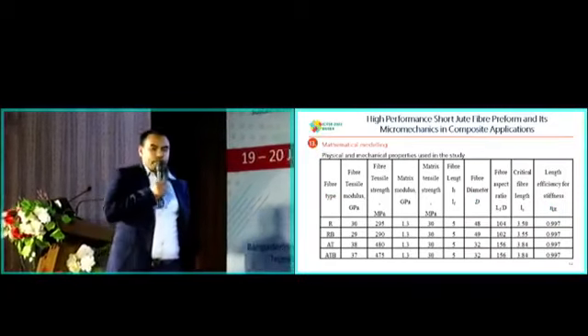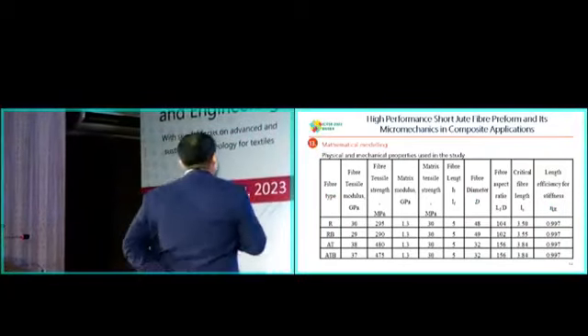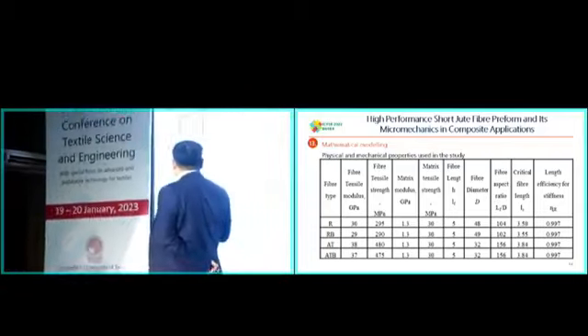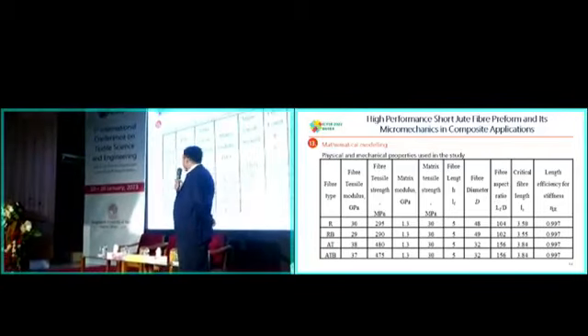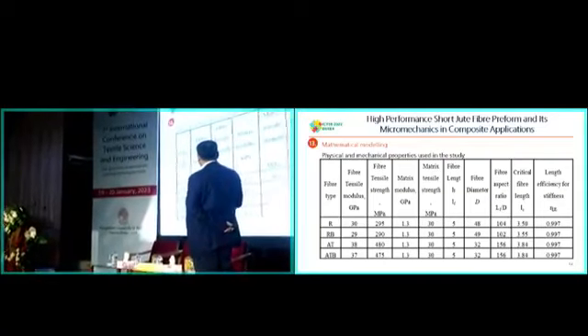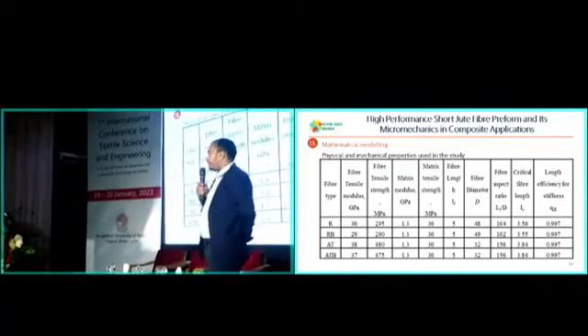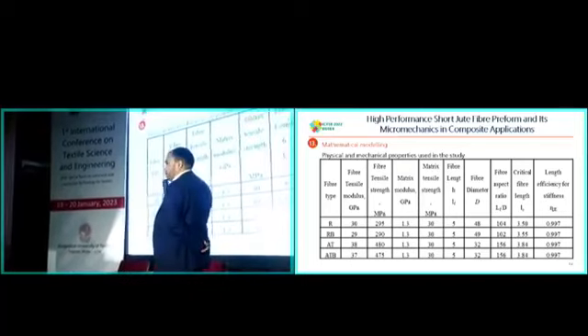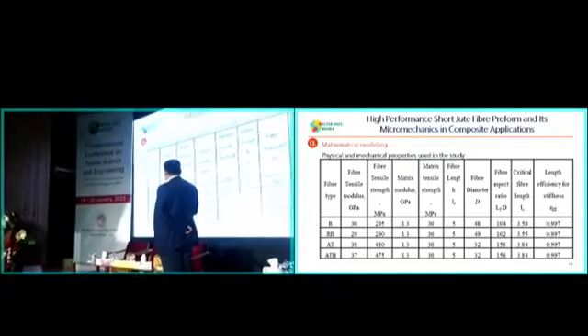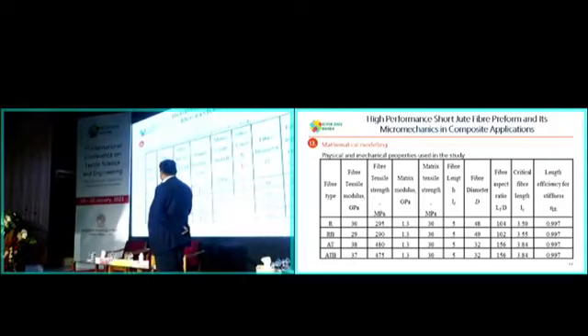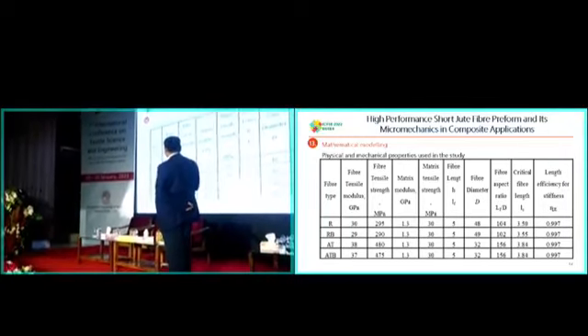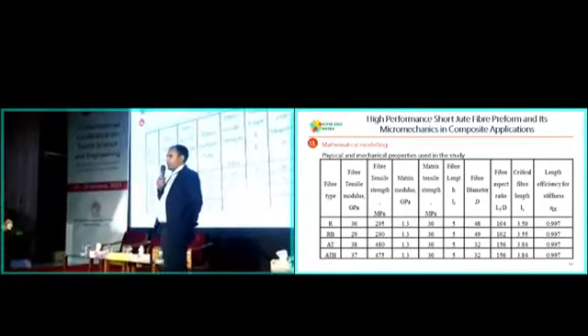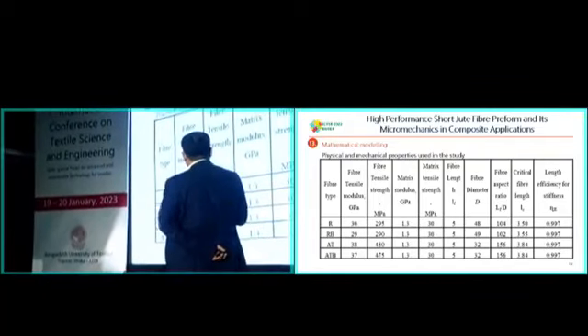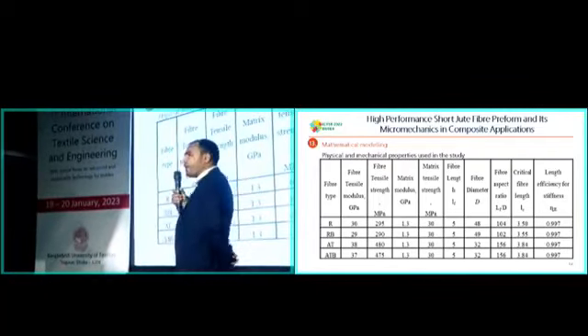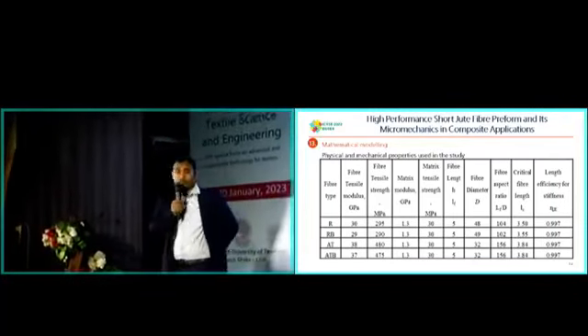Before doing the mathematical modeling, we considered some of the physical and mechanical properties of the different fibers produced in the laboratory. For the raw fibers, the tensile stiffness is 30 GPa. When treated with the binder, it gives 29 GPa. When you treat it with the alkaline solution, the stiffness is 38 GPa, and it is also 37 when you apply the binder. The tensile strength changed significantly, increasing from 295 to 475 or 480 maximum after applying alkali treatment and individualization of the fibers using our laboratory-made device.